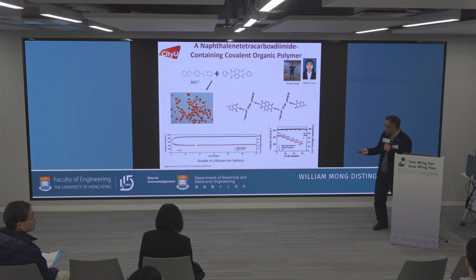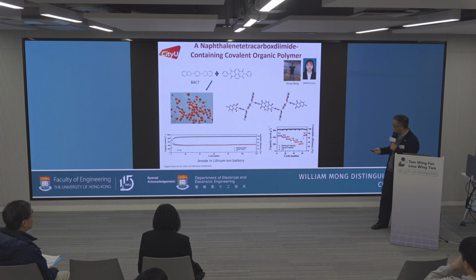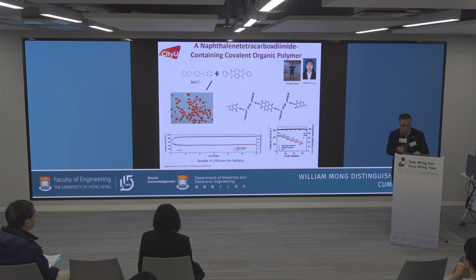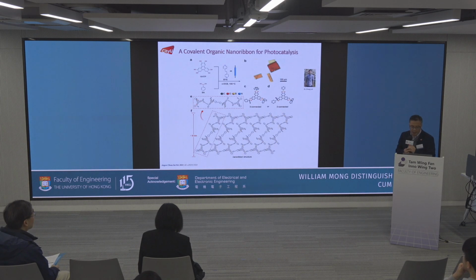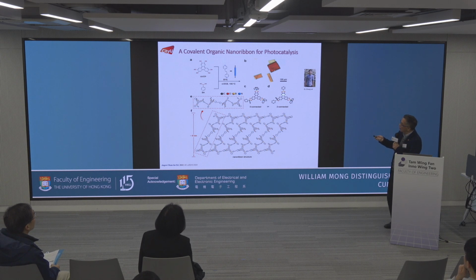So now we use this as an electrode, and we do the rechargeable battery. You can see that we cycle more than 120. Here I only show the 120. In our paper, we can cycle more than 20,000, and this is at different charge currents. It also shows a very good performance for these polymers. And then keep going. My postdoc, Dr. Zhang, worked on another way.